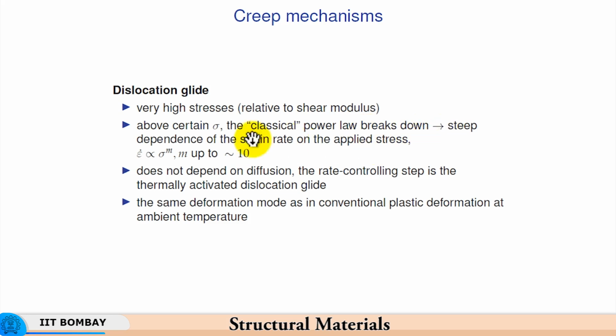It is no longer valid because much higher stresses are needed in order to generate the kind of strain rate, the same deformation mode as in conventional plastic deformation at ambient temperature. So, here one would expect this at very low temperatures, because you have high stresses relative to shear modulus, and here the dislocation activity would be the maximum, very significant, and very little temperature effect or very little effect of diffusion related phenomena would be found at relatively low temperature. So, low temperature creep would essentially mean a creep by dislocation glide.